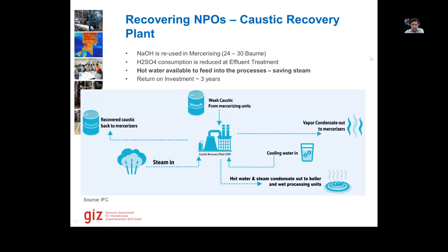I can show you one case study that was done by IFC, where one factory installed a caustic recovery plant, with the weak caustic from the mercerizing unit coming in. Steam is also applied to this process and cooling water is going into it. We have recovered caustic going back to the mercerizers. We have vapor condensate out, which is collected from the top and also goes to the mercerizers. Hot water and steam condensate goes back to the boiler and wet processing units, depending on where it can be used.